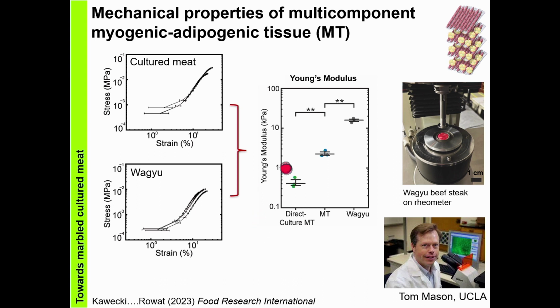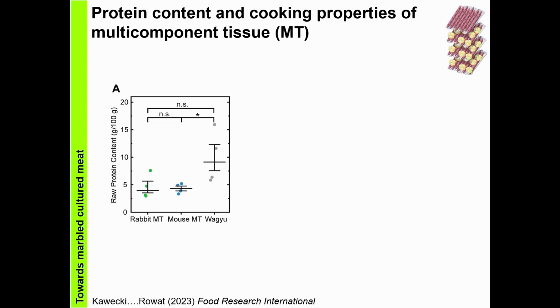So when it comes directly out of culture, it's clearly more compliant than the conventional Wagyu beef, which is also more dehydrated and aged more than the multi-component tissue. So while we see overall qualitatively similar stress-strain response, the tissue is not falling apart. It's showing behavior of a viscoelastic solid. We do see that we will be able to tune the texture, I think, by tuning the water content of these samples. So I think lots of interesting areas for study in the future.